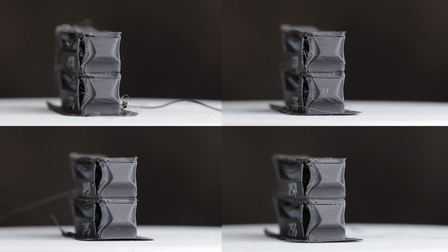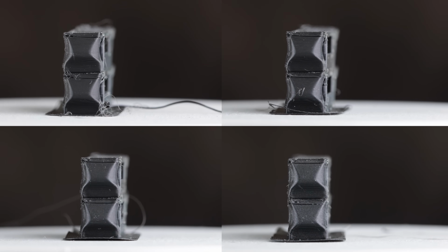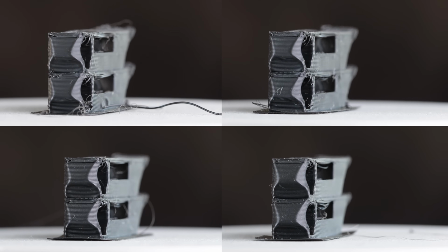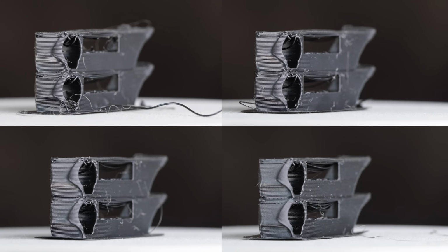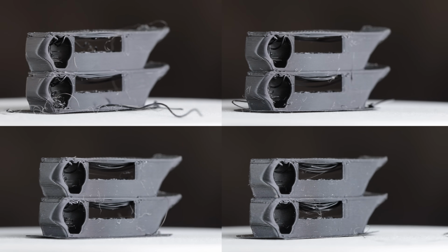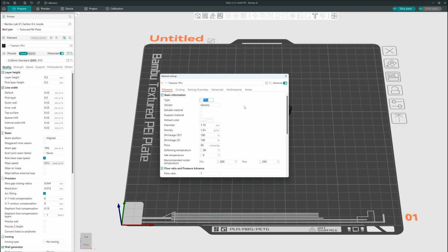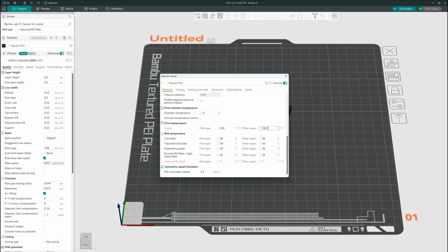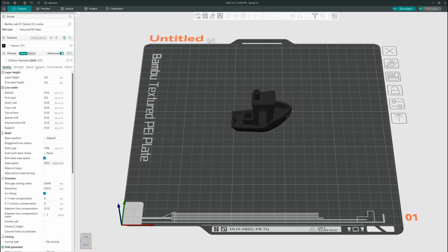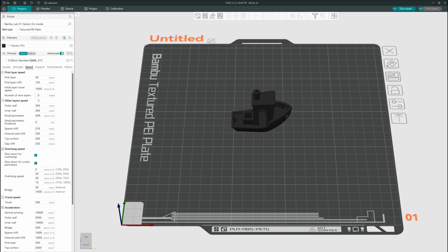I find that the print at 250 degrees Celsius looks the best. The circular hole on the side is the cleanest at this temperature. So in the slicer, I set the nozzle temperature for other layers to 250 degrees Celsius. I kept the first layer at 230 since the adhesion to the print bed is already quite strong. I also reduced the speed for inner and outer walls to 10 mm per second before printing another Benchy.